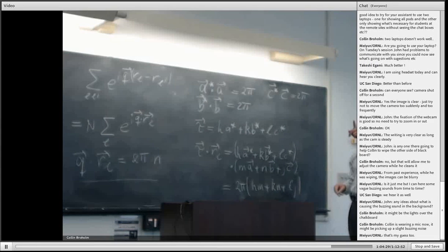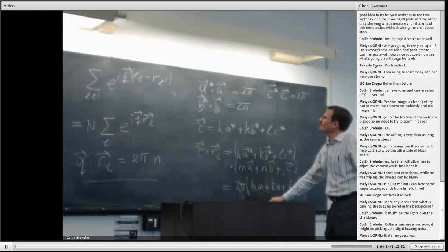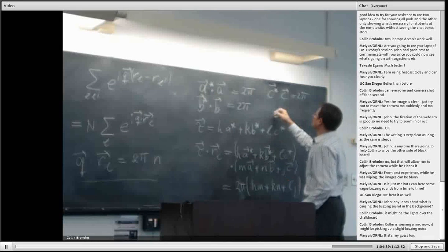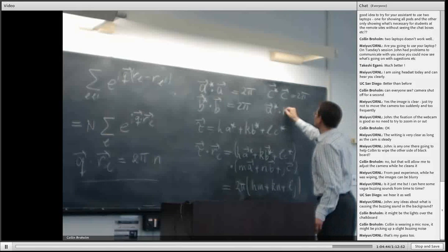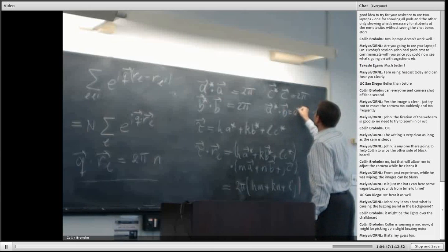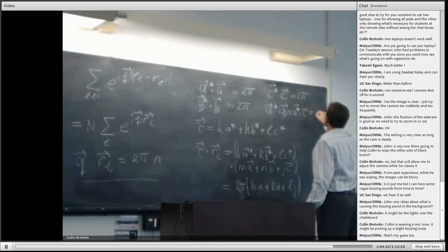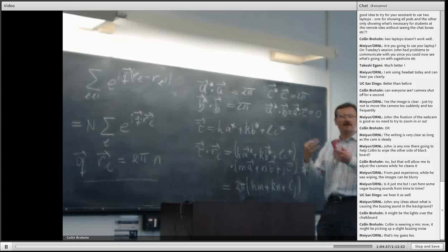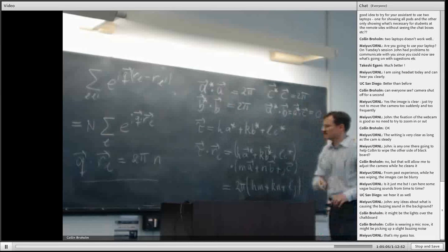Now, I forgot to mention one thing. I should have mentioned that this is not the sufficient condition. Apart from these dot products being equal to 2 pi, I also want to ensure that all of these off-diagonal terms, if you will, A star dotted with B, should be equal to A star dotted with C, should be equal to 0. So I need to be perpendicular to two of the real space directions, and I need to have a finite component along the other direction, and I'll arrange for the length of the reciprocal lattice vector so that the corresponding dot product becomes 2 pi. So that's the reciprocal lattice.